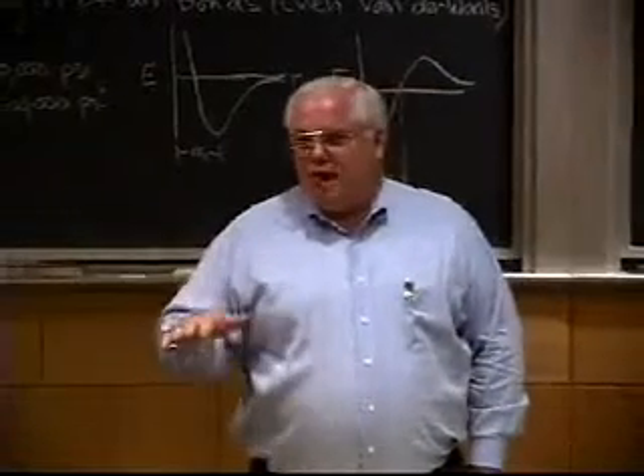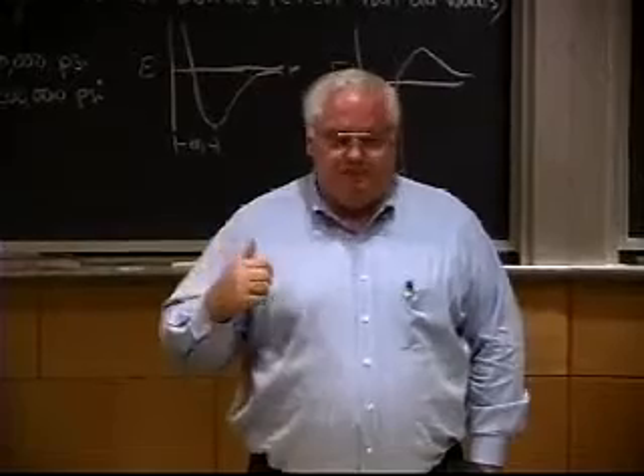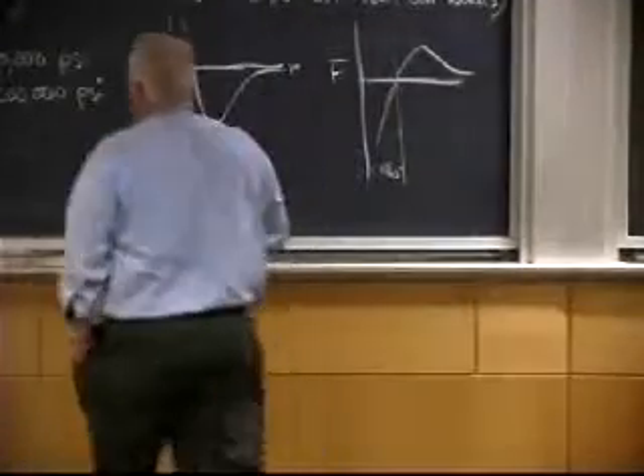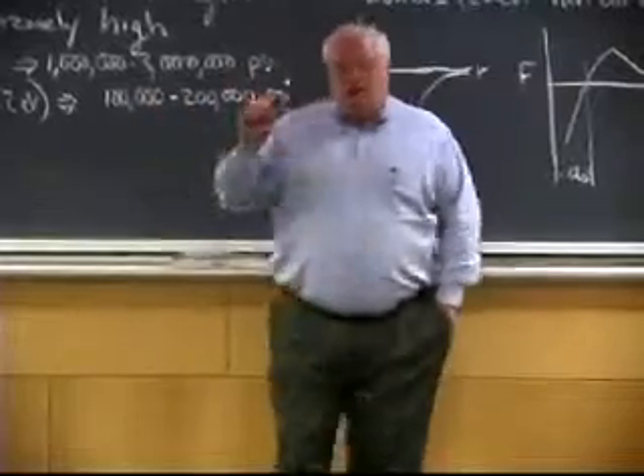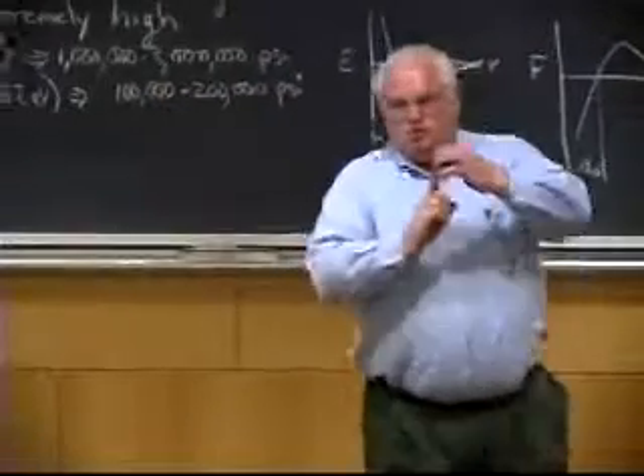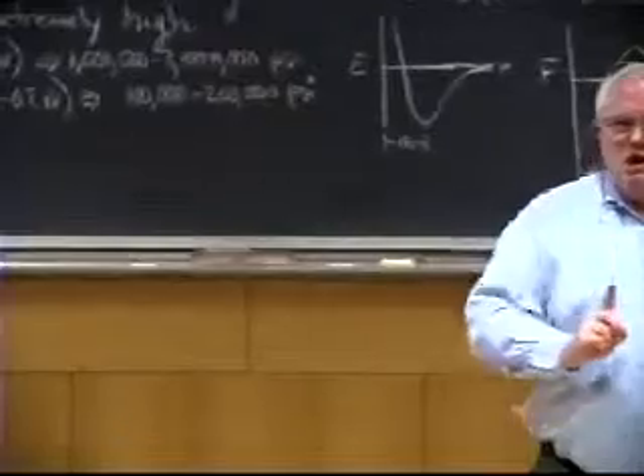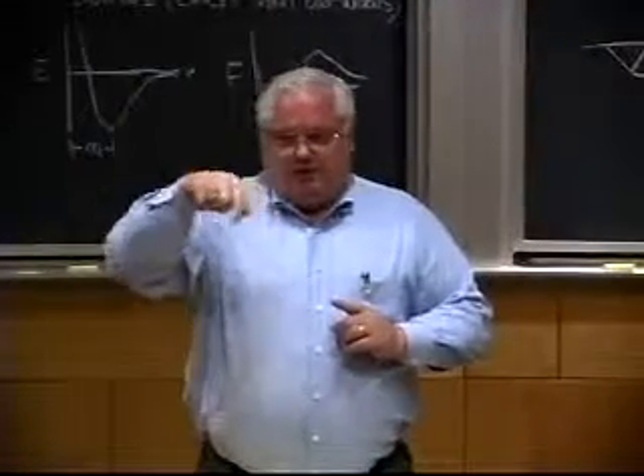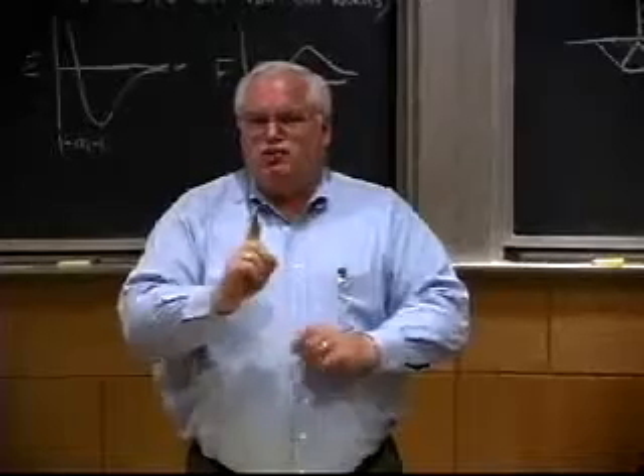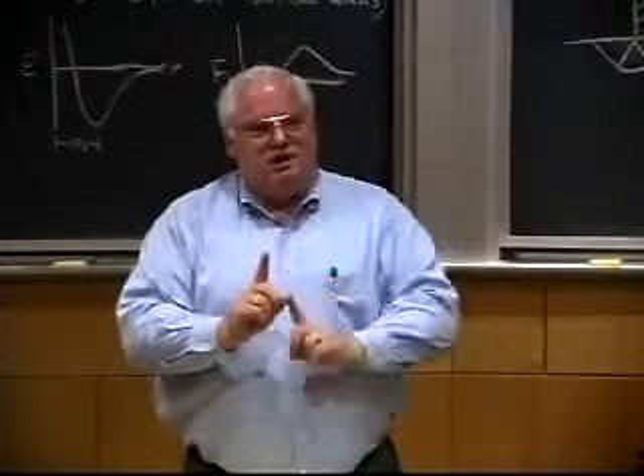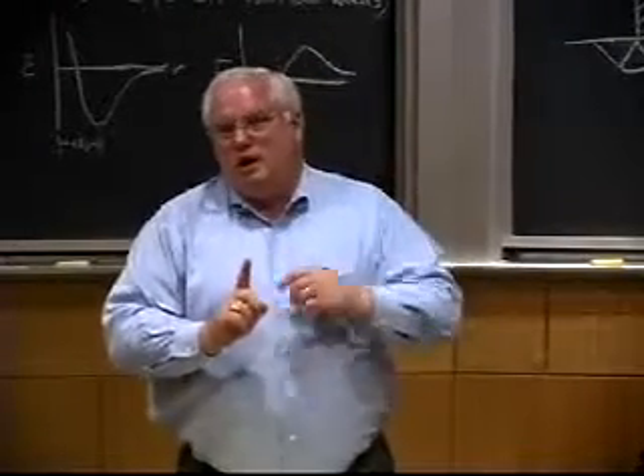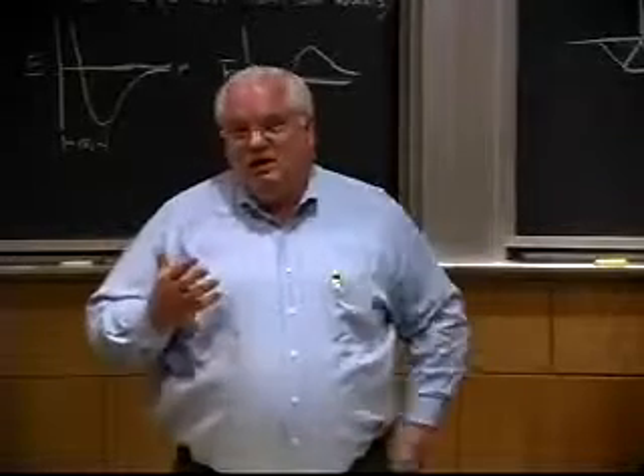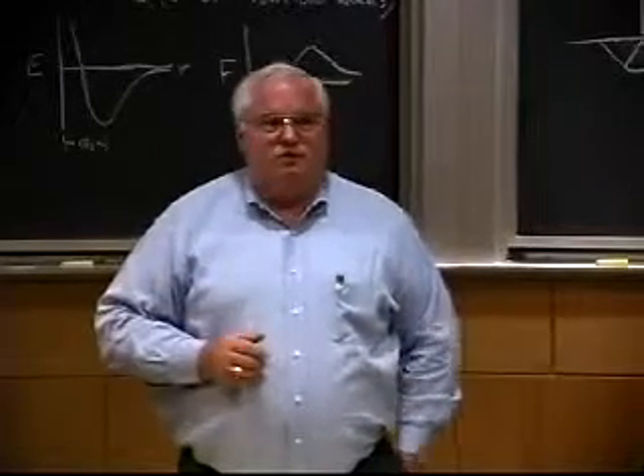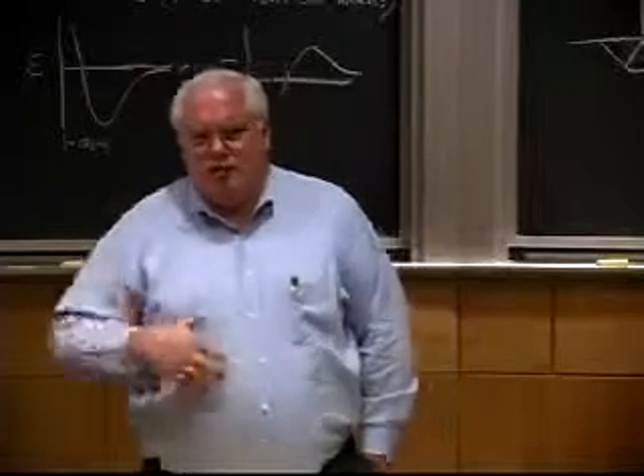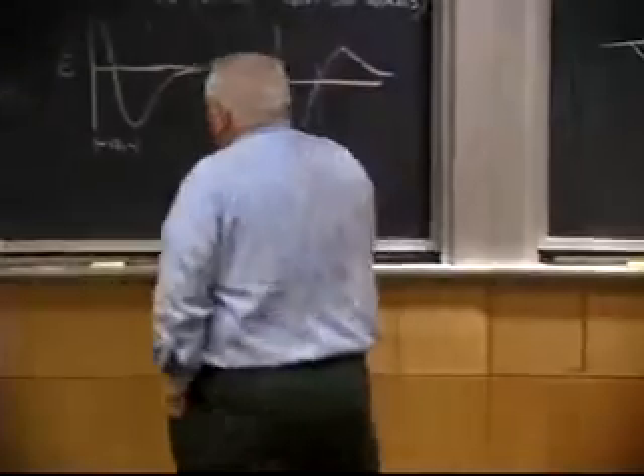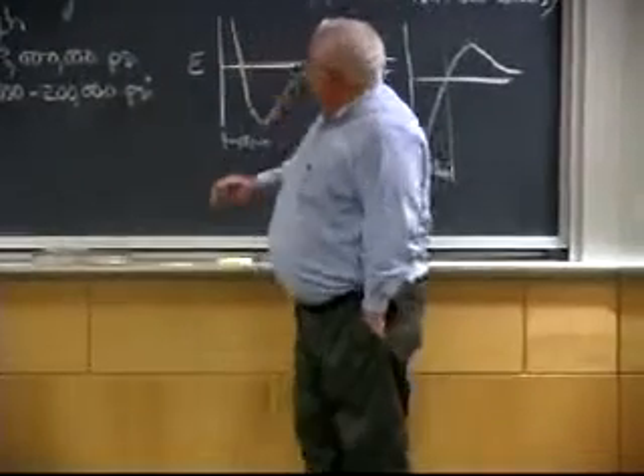But in fact, we know that polymers, plastics, don't have anywhere near that strength. We know that metals don't have anything near this strength, except I did mention that iron fibers, iron whiskers, which are little perfect crystals of iron with only one dislocation coming up through the center, called a screw dislocation. When you pull on it in the long direction, that dislocation is lined up, and so it can't move. And you can get 2 million psi in an iron whisker. And this guy Smalley at Rice University has predicted that carbon nanotubes will have 2 million psi. Well, they probably will, if anyone could do a tensile test on them to prove it.